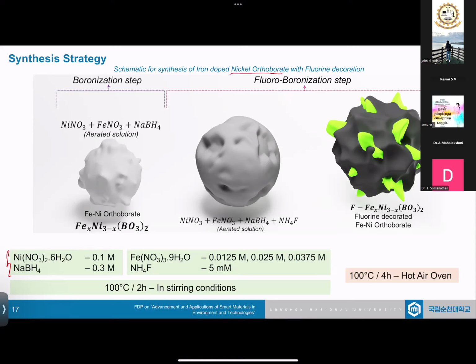We stirred it, and the boron source was added dropwise while it was at 100 degrees Celsius for 2 hours, in a very sequential, proper manner, where we added only 200 microliters per iteration, with a gap of 30 seconds between each addition. In that way, we added the boron source, and we then left it to stir for 2 hours continuously, because we wanted it to properly react and form the orthoborate system.